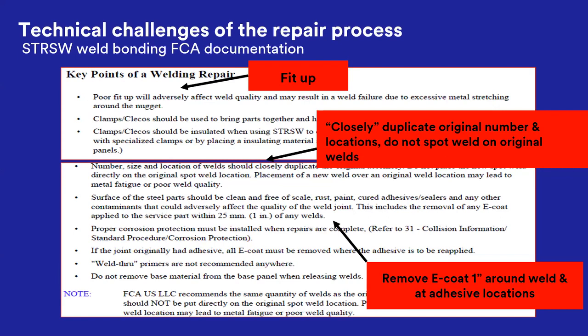Also, as I mentioned earlier, closely duplicate the number of welds and the locations. Some manufacturers caution against welding in the same location twice. Now, there may be times where you have adhesive between the two bottom panels and you're putting a third panel over the top. In that case, some of the manufacturers may recommend welding through the original location. Otherwise, you have adhesive insulating the two bottom layers. So it's all different by manufacturer. So make sure you're checking out those details in their information to know exactly how they want that done.